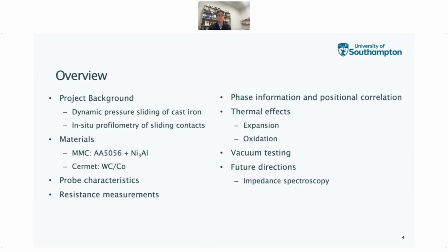So we'll look at the probe characteristics and then how you can use that to perhaps elucidate some of the resistance measurements that we make. And then whether we can actually correlate that spatially with the position of those phases in the surface. Now, some of the challenges we face are often thermal in this regard, and that has effects that we have to take account of. So thermal expansion is one of them, and also oxidation of the surface. But then we'll move on to looking at vacuum techniques and how that might mitigate some of those. And then I'll just finish with some of the future directions we're currently looking at in terms of applying alternating currents to the surface.